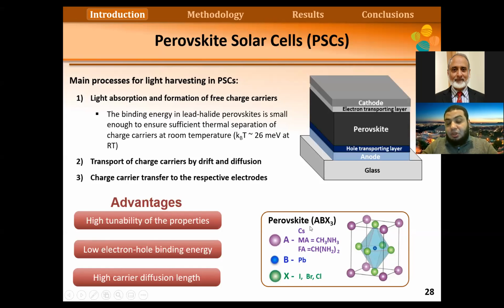With the change of the structure, we can have completely different properties. We can tune the absorption, we can tune the conductivity, we can tune everything based on the choice of these materials. And also it has a low electron hole binding energy. Most of these materials, just at room temperature, we can have free electrons and holes after absorption. And also they have a high diffusion length, so we can have a very thick film without the problem of diffusion length. I think for organics also, it has a problem with diffusion length. The excitons can move only a small distance before recombining, but for this one, the diffusion is much longer. It can reach micrometers. So the charges can move micrometers without recombining. So this is also a good thing for this material.